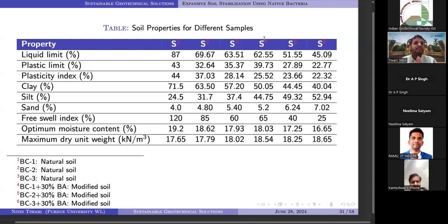And then we modified 3 more soils, which are S4, S5, and S6. They are the modification of each soil. We added 30% of bottom ash. Bottom ash is an industrial waste. We have almost 7, 8 thermal power plants, and I still remember we visited several of them with Nilima ma'am. We visited the dikes and figured out that pond ash and bottom ash are a big problem, and we used that bottom ash, to be honest. So we modified with 30% bottom ash. Now we have a total of 6 soils.